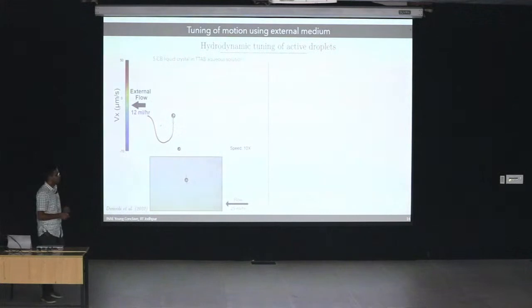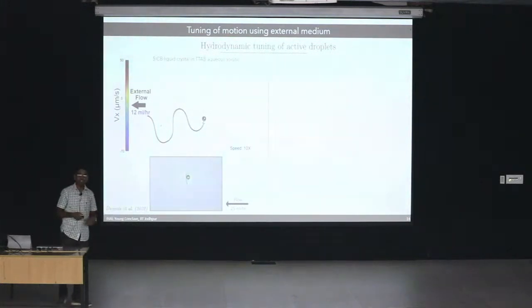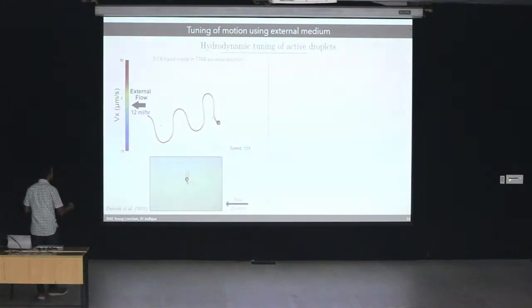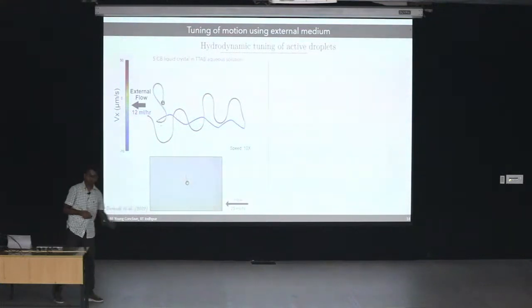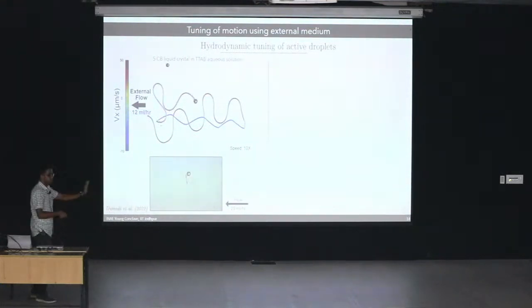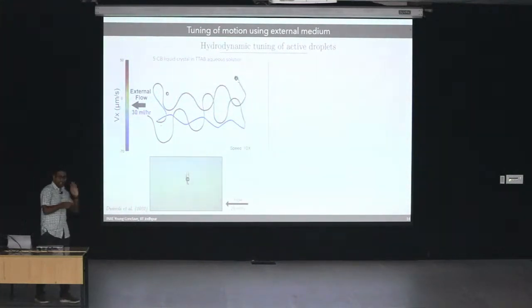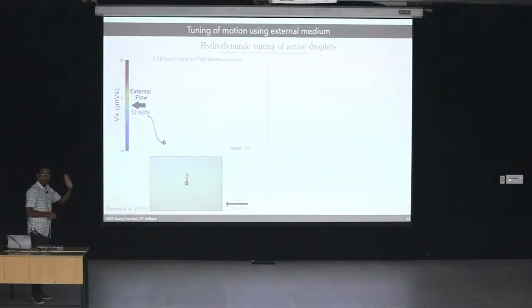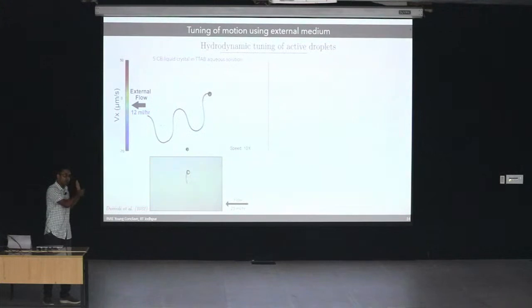Similarly, we can also look at the motion of active droplets in flow, and this is a very nice work which we recently published. Here we are maintaining a flow from right to left. When the flow is 12 milliliters per hour, the droplet is migrating against the flow. When the flow is high, it starts to drift with the flow. And by very careful manipulation of these flow conditions, we demonstrated that we can trap the droplet between two particular locations. So you are still flowing the liquid, but the droplet is settling between two different points.